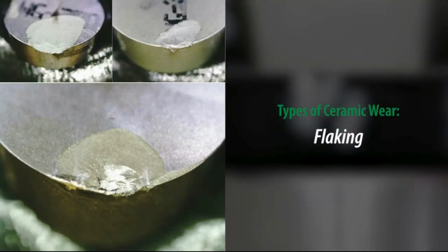This image of flaking shows that it's a more severe version of chipping. This may indicate the speed is too low to reach optimal strain rates and plasticization, or the chip thickness may be too high, which would result in excessive mechanical stress and too much heat leaving the cutting zone with the chip. Prolonged flaking may lead to top slicing.